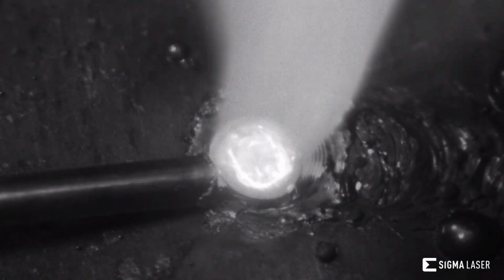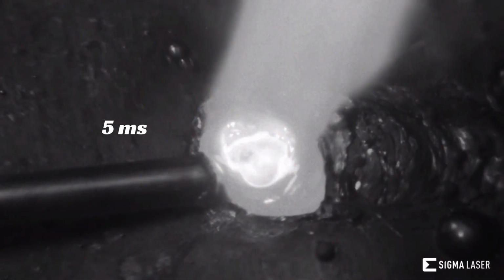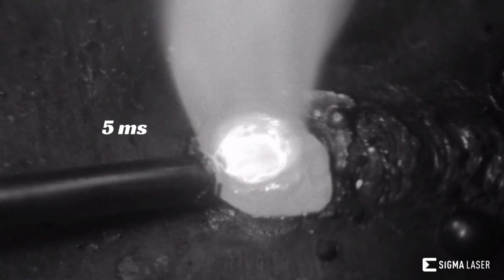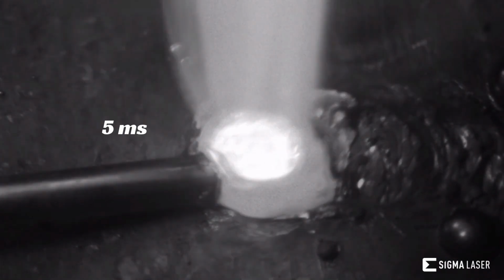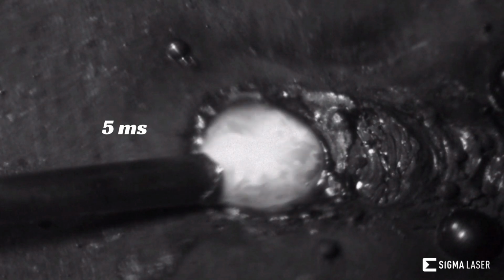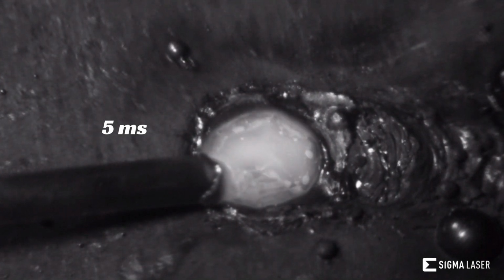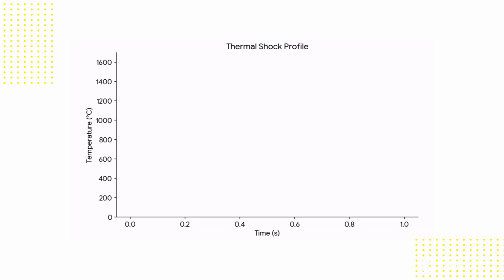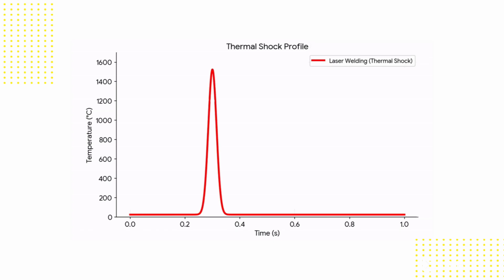Here, we see a single laser pulse with a duration of approximately 5 milliseconds. The molten pool reacts turbulently. It begins to boil. It loses stability. Energy is introduced without control. After the pulse, temperature drops abruptly. What becomes visible here is a thermal shock. Without control, the pulse overheats the weld spot and causes a thermal shock.